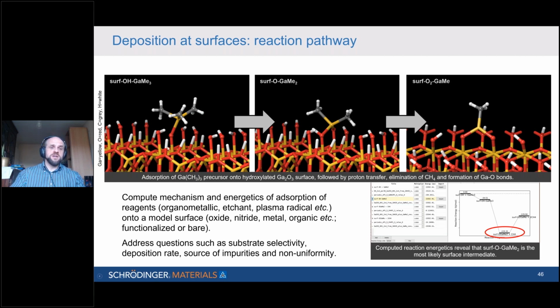You can see on the left the molecule chemisorbing to an oxygen, and then proton transfer takes place, and one of the ligands desorbs as CH4, and we're left with a dimethyl gallium fragment, and it starts to bind more to the surface. You see gallium-oxygen bonds are forming, and another ligand is lost, and another gallium-oxygen bond forms. So this process of reactive adsorption, or dissociative adsorption, or adsorption followed by desorption of ligands, this is actually the growth process. This set of chemical reactions, one after another, is how the growth takes place.